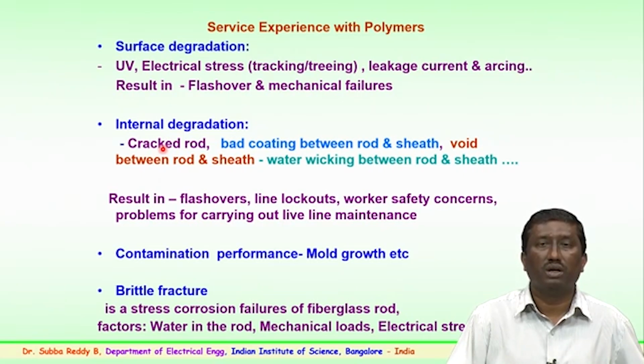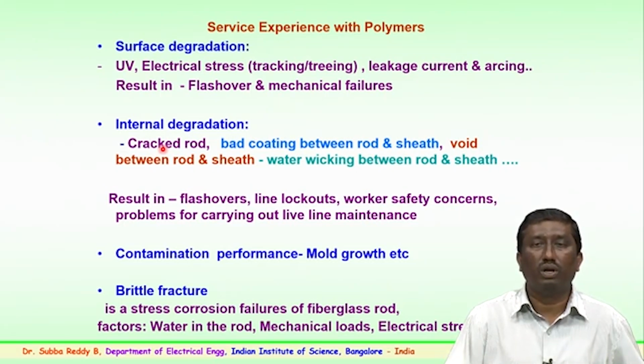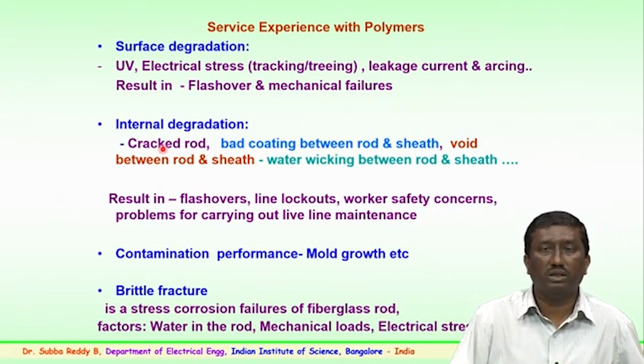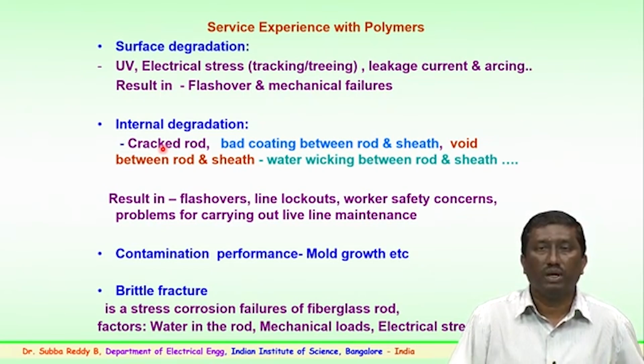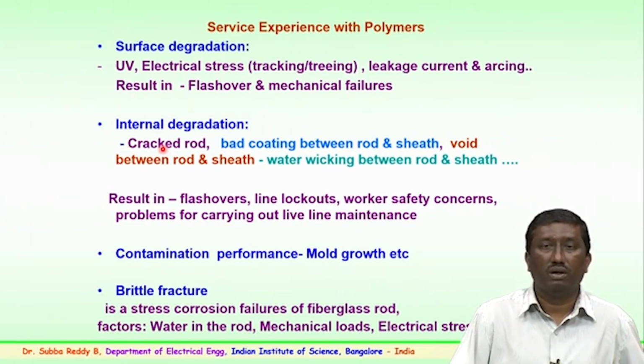Service experience has shown that water could enter through very small blowholes or holes, and on reaching the surface of the rod, nitric acid formation is seen. Because of this nitric acid, rod and sheath failures have happened, where brittle fracture of the insulating rod could occur over a period of time. So, these have also been seen in the field.